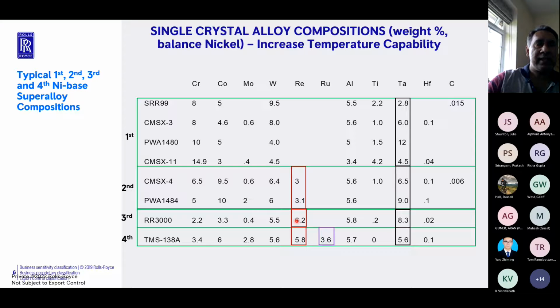Now, the problem with increasing the amount of rhenium that you add from first to second to third generation alloys is that it has two problems. The first problem is as you add rhenium, you increase the instability of this alloy. So basically, if you operate this alloy at a high temperature, say around 1000 degrees, for several hundreds of hours, you form unfavorable phases which are detrimental, like for example, topologically close-packed phases, or commonly called TCP phases. So third generation alloys are good in terms of strength, but their strength will deteriorate over a period of time because of the added amount of rhenium.